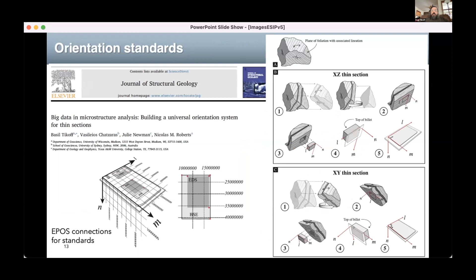Standards were a challenge since nothing was developed before we started. A lot of our earlier work went into figuring out how to get from a natural thin section into a coordinate system based on the reference micrograph. We basically said it's just like a UTM grid but for a thin section, given in microns. The L, M, and N directions in space are given by direction cosines — three orthogonal directions — providing a way to connect the thin section 3D grid back to its spatial orientation in the field.